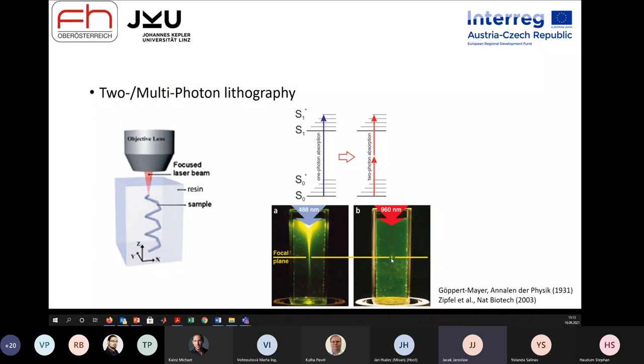In this case, this 2 photon absorption allows us basically to only excite our photoinitiator in a small volume inside of the focus, and this is a nonlinear process, which means the localized excitation is proportional to the square of the irradiance.